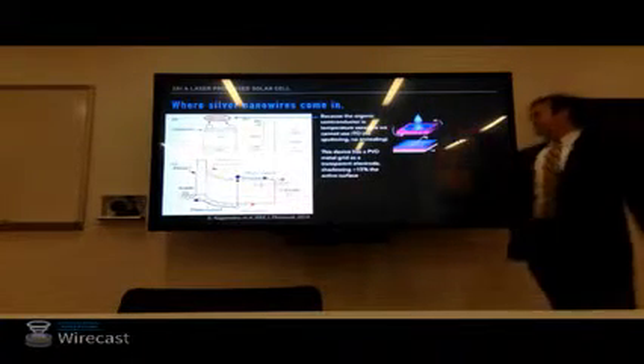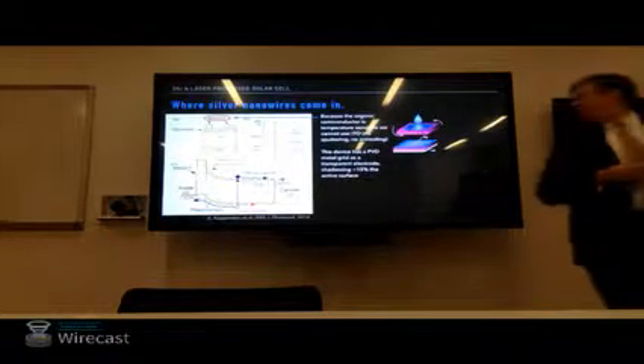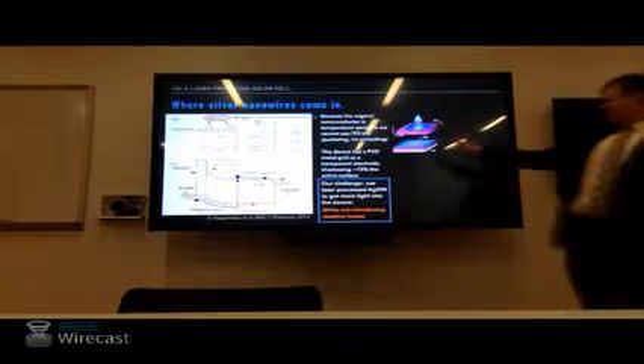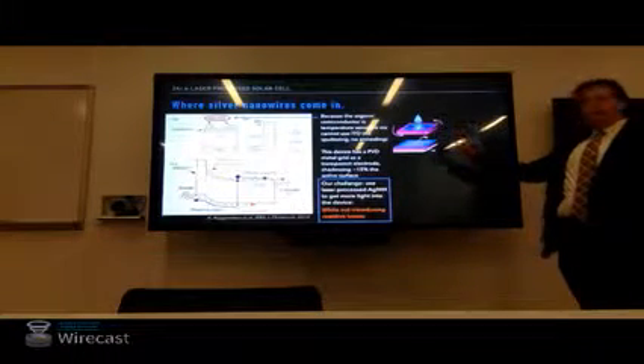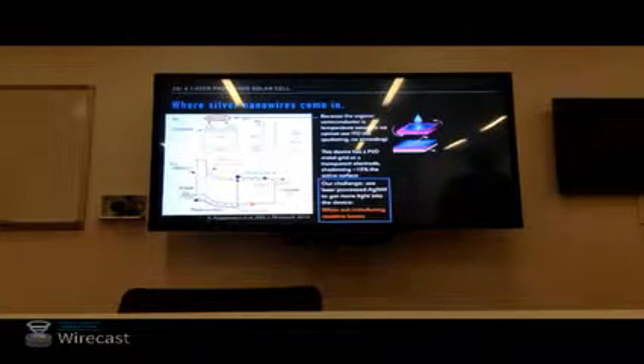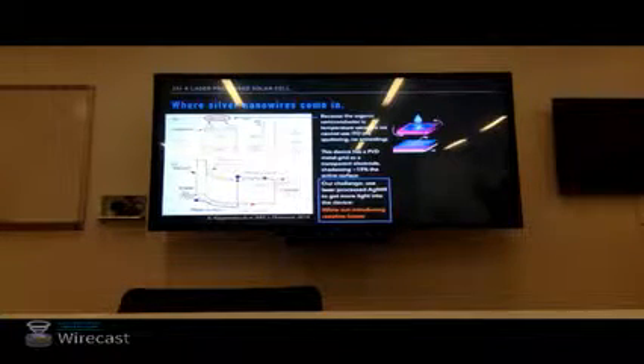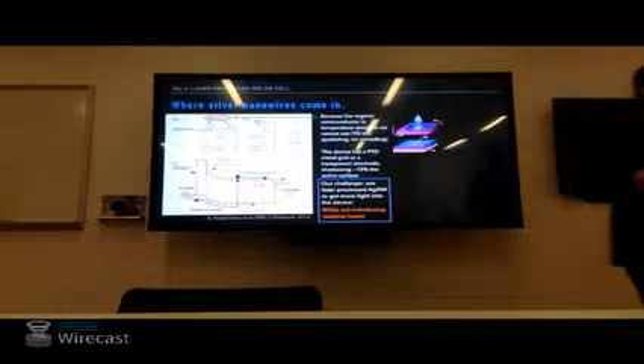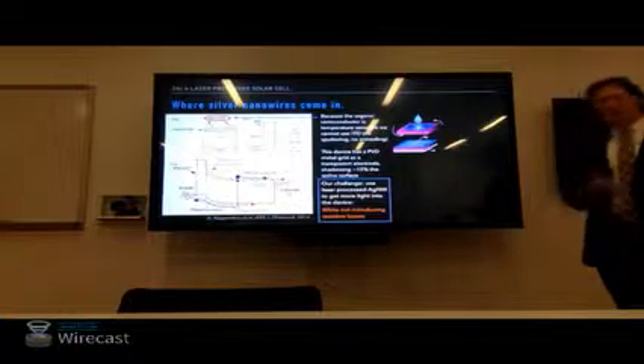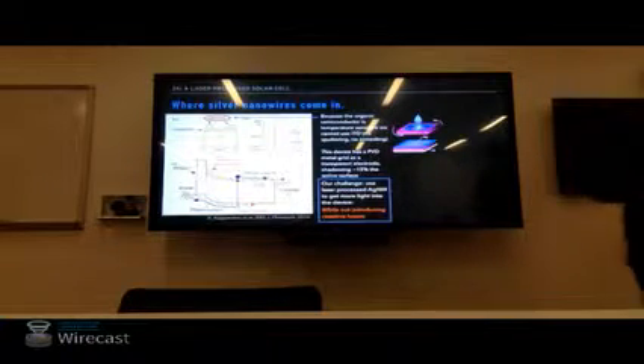This is the processing scheme. The PEDOT is spun onto the wafer, and then physical vapor deposition for the metal contacts. A typical bus bar on these will shadow about 15% of your device. That means that area is thrown away. We're not using that to collect sunlight. Our challenge is to use silver nanowires to get more light into the device, pulling more current out of the device. Our challenge is not introducing resistive losses, whether in plane or across the plane.